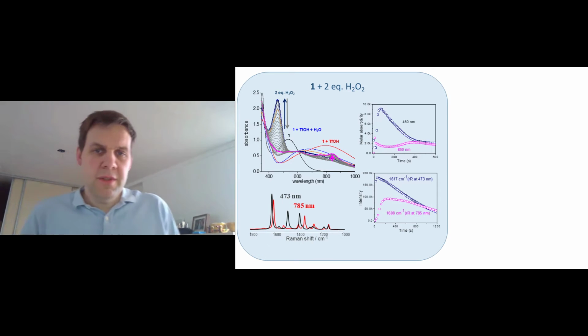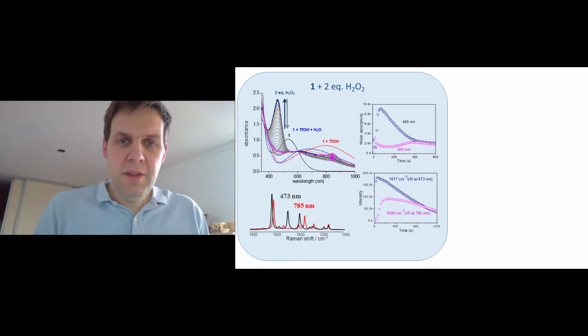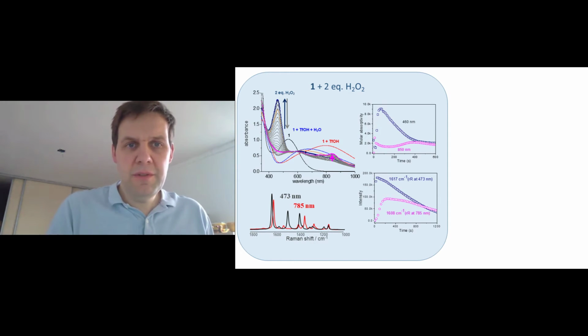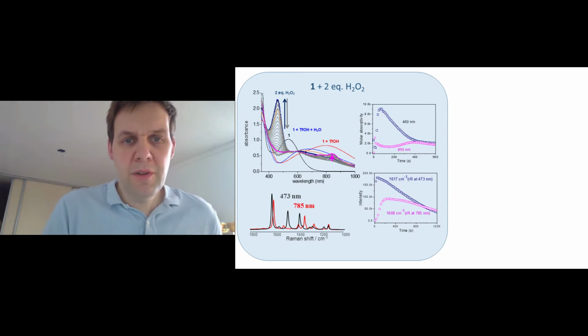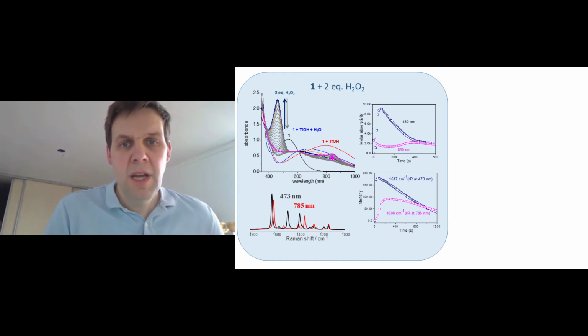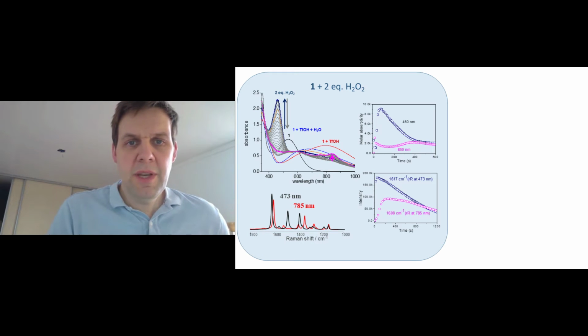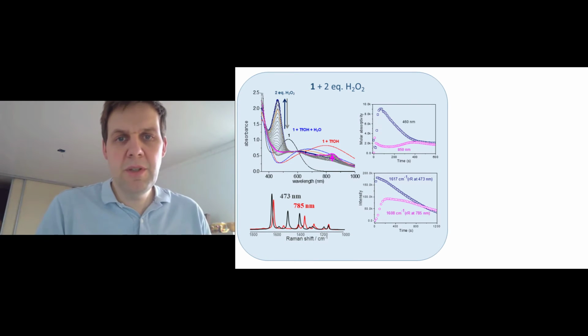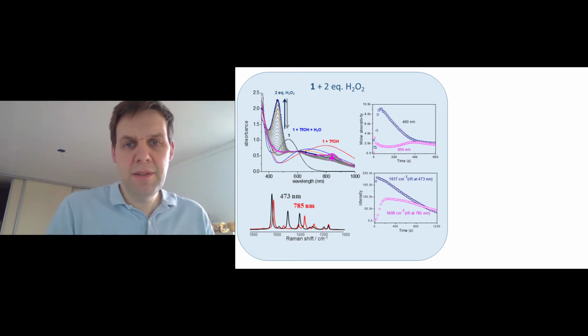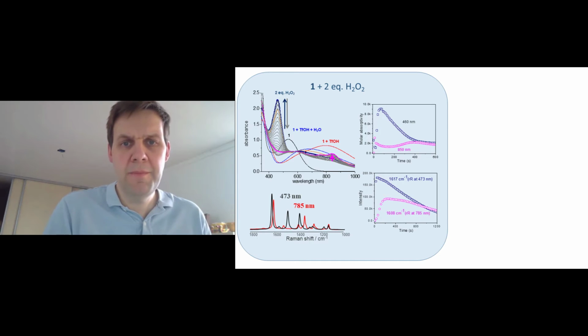One other thing to notice is if we follow the Raman intensity over time and take into account inner filter effects, remember there's a very high absorbance here, so your Raman intensity will be affected by inner filter effects, so you have to take that into account. We actually see very different kinetics than we get by UV-vis absorption. And the good thing about Raman spectroscopy is you look at individual bands. You can pick bands which don't overlap, whereas with absorption spectroscopy, you get a lot of overlap between different bands. So following by Raman spectroscopy actually gives us a proper insight into what's happening during the reaction.